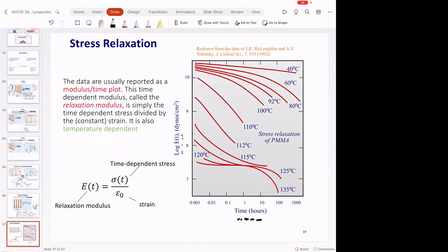And you can see for this polymer sample right here, here's PMMA right here. So it's polymethyl methacrylate, 40 degrees. This is the zoomed in part, or this is a linear scale, but it's plotted as the log of the number. But this up here, compared to this, is not too much of a change in terms of how much stress relaxation over hundreds of hours you get for PMMA. So the modulus changes a little bit, or the stress relaxation happens a little bit at 40 degrees Celsius. Of course, as you heat up the polymer, the modulus at time zero goes down, or effectively time zero. We can't plot zero on this log scale, but you heat up a piece of PMMA and the modulus is lower at 110 degrees than it is at 40 degrees.